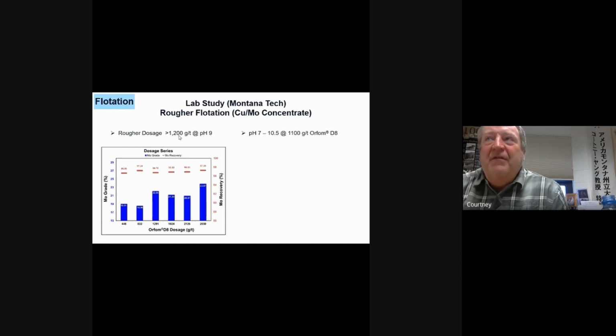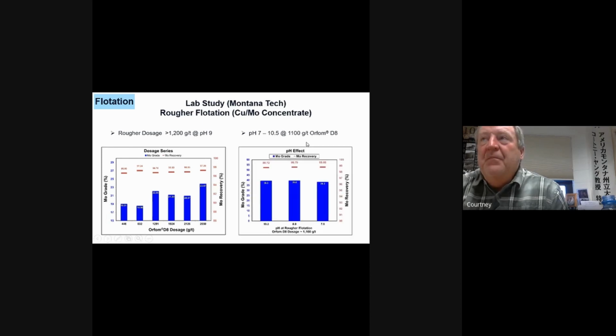So let's take a look at the effect of pH, and we're going to keep the dosage constant now at 1,100 grams per ton. And you can see that in this case, we're getting really good moly grade, 39.3, 39.6, and 38.3, and it seems to work best at a moderate pH. You go too low, it works, of course, there's nothing wrong with that, and it works at higher pH. But moderate pH is okay. And if you remember back at the zeta-potential studies, pH 8, 8.5, 9 seemed to work quite well. Okay, and again, look at those recoveries. Excellent recoveries for all the pHs.